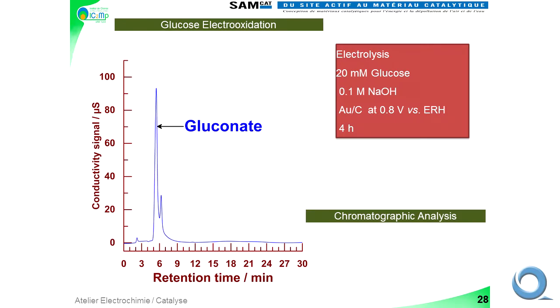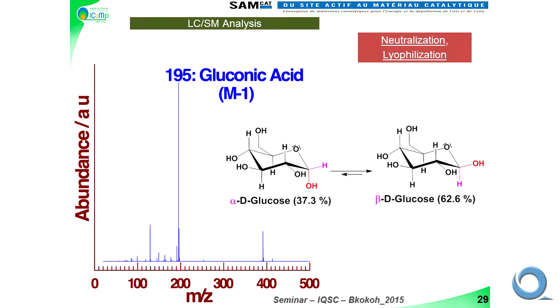And we can see the decrease of the current. We remove, as we did with glycerol, and the remaining product, after lyophilization and neutralization, and after we recover it for mass spectrometry, we have in chromatographic analysis this gluconate by comparison with the reference. And after we recover the solid product after lyophilization to inject in mass spectrometry, we use negative ionization of the system. We have here, for example, the mass of gluconic acid minus a proton.